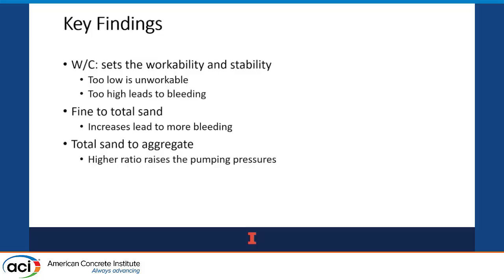So, what were the key findings? Well, it all boils down to water cement ratio. It really has a big effect on the bleeding. If you get too low, you reduce the bleeding. If you get too high, you get more bleeding. And what we've seen time and time again with many of these tests, and it's been confirmed out in the field too, is if these mixes are allowed to start bleeding, all of a sudden you start to pack the material, and that's when you start clogging pumps. That's when the extrusion head no longer wants to do its job.